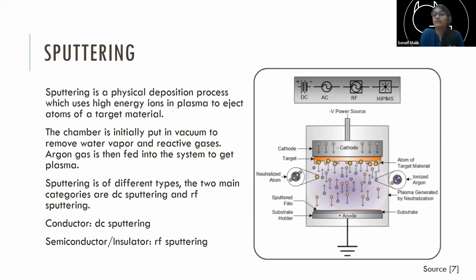If the frequencies are very low, then at that point it is kind of close to DC sputtering. Again, you will have charge accumulation on your target, and the plasma might also not sustain, because if argon atoms keep striking here and you have an increasing DC bias, again there will be a power discharge. So radio frequency fits in the balance, and also it is easier to match the impedance for radio frequency. It has been highly studied.